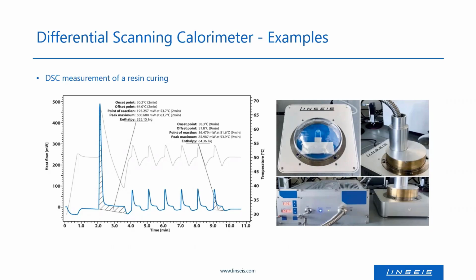So in the first peak, you see a clear difference to the last one, and in the last peak, the area was the same as in the peaks before, so that the area reached a plateau, so that the material was cured completely. And the area under this peak was used to calculate the heat of the reaction and the enthalpy for the curing.